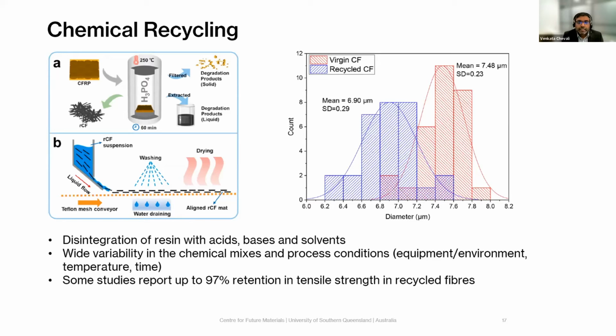However, as with any size reduction method or recycling method, there is a loss of the original form of the fibers. And in this particular case, what you're looking at is the mean or the peak of the distribution of fiber diameter for the virgin fiber being higher than the recycled carbon fiber, which means that there is a degradation in the fiber length and thereby the fiber aspect ratio. So again, that would directly correlate to a lower structural bearing capability when you are using the recycled carbon fibers. But in some cases, you can also see about a 97% retention in the tensile strength, which is pretty good.